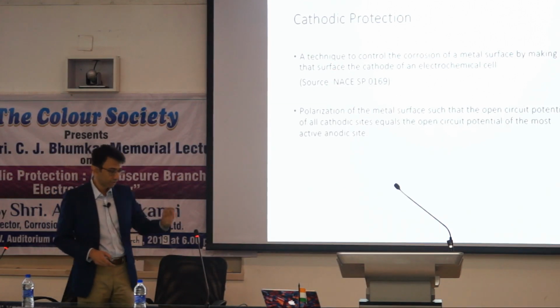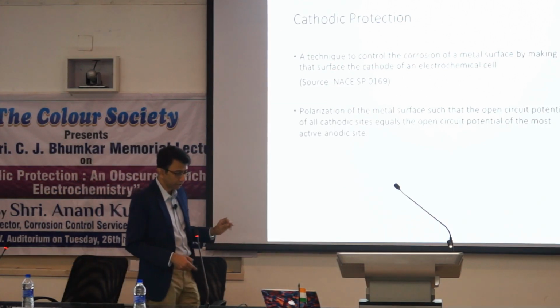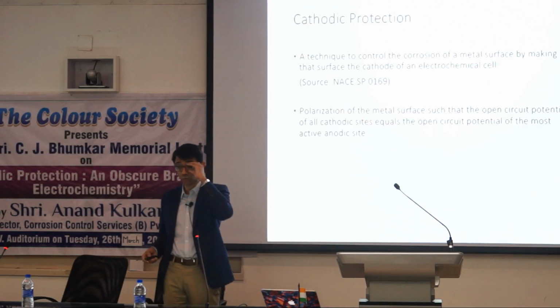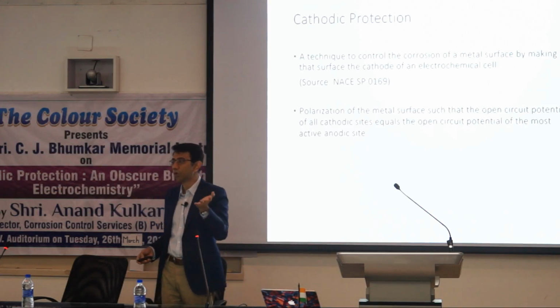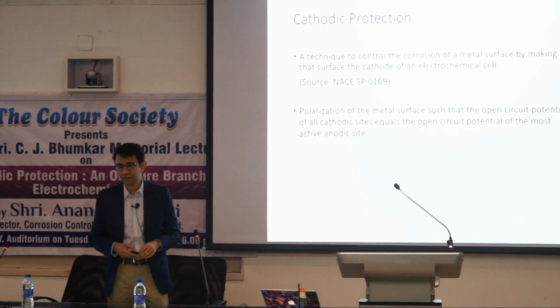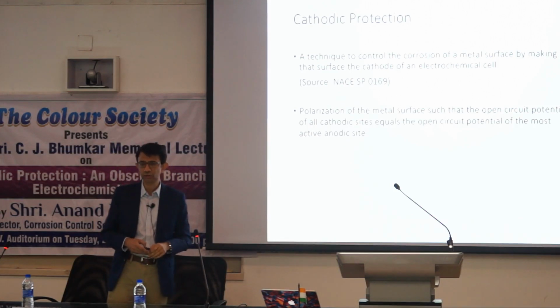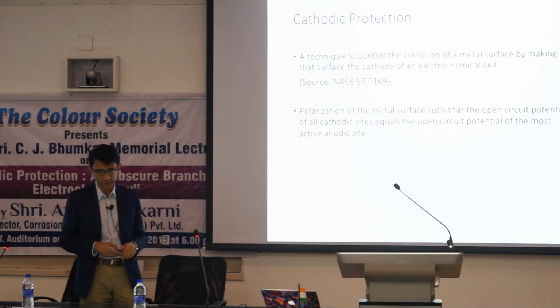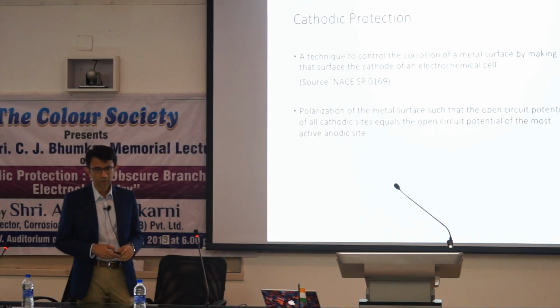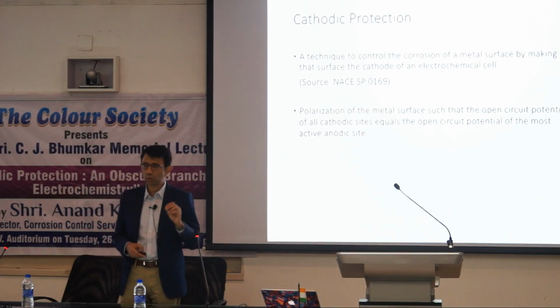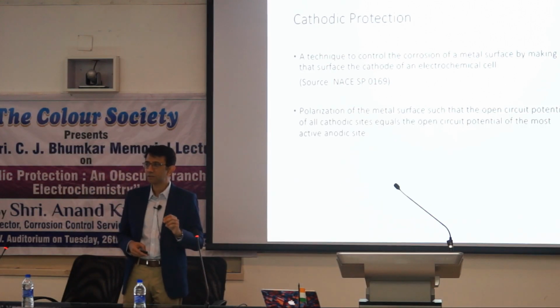So if you have a pipeline that is coated, and all pipelines today are coated, we have excellent coatings. We have fusion bonded epoxy, we have 3-layer polyethylene, extremely high electrical resistance, high dielectric coatings, which form a fantastic primary barrier to corrosion. But in and of themselves, they are not sufficient to prevent corrosion, simply because the better the quality of the coating, the greater is the risk of corrosion.